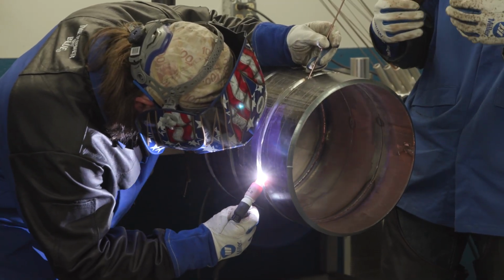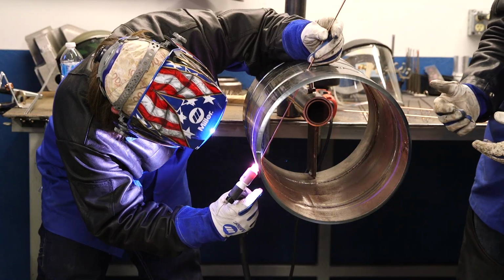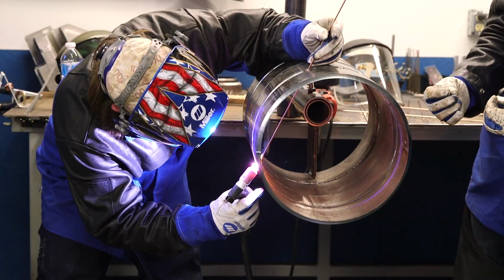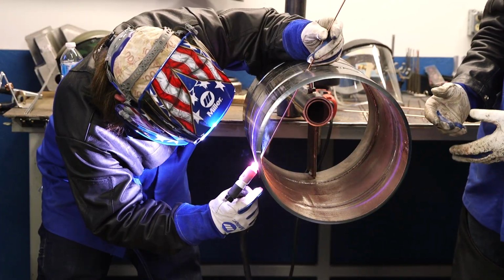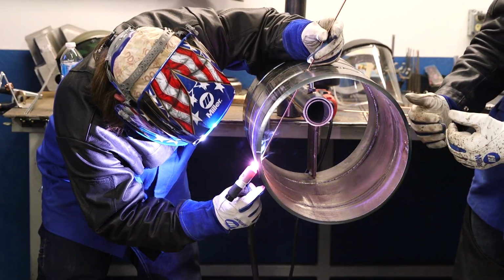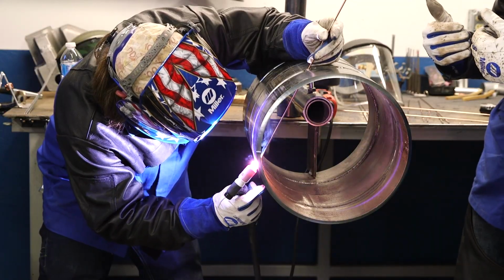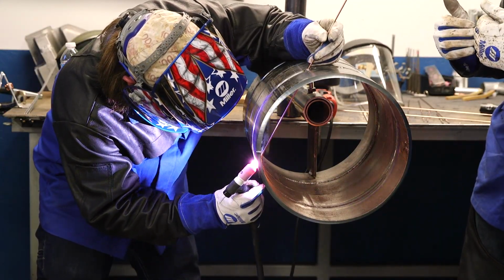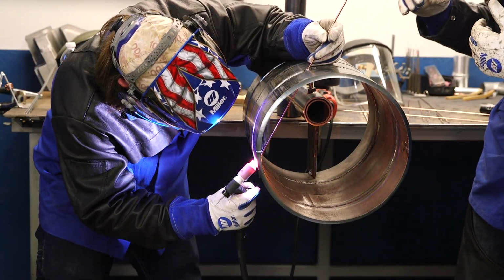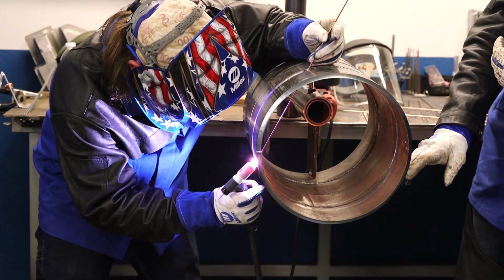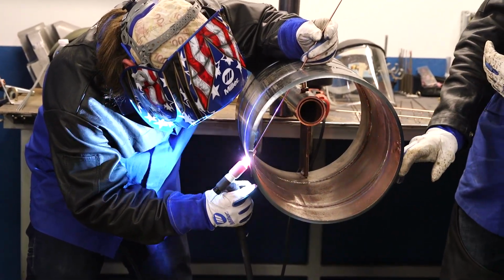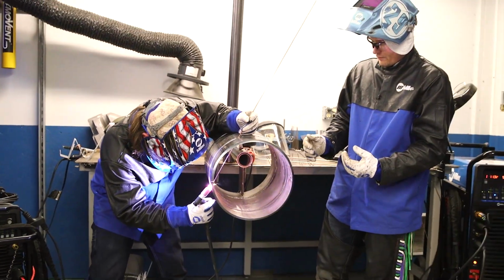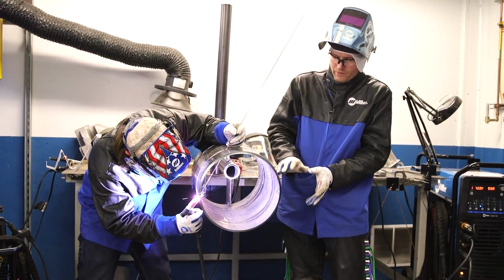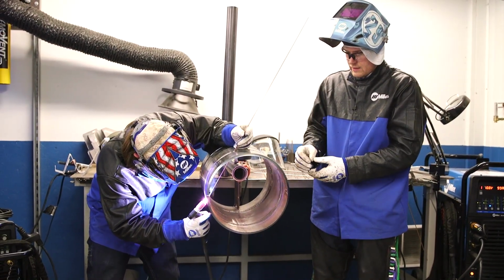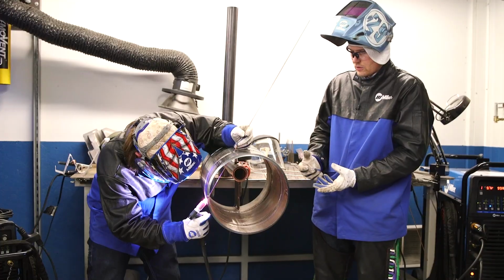And actually what happens is that when it starts closing up on you, a lot of inexperienced welders will still try and weld with it, and they figure they can just see a keyhole and keep going, but they actually see a false bevel tip. So they see the bevel tip, and then the filler metal can't go onto the leading edge or even outside of the weld puddle because the gap is closing up so much. It actually ends up a very non-uniform root, very heavy root pass, loss of control.